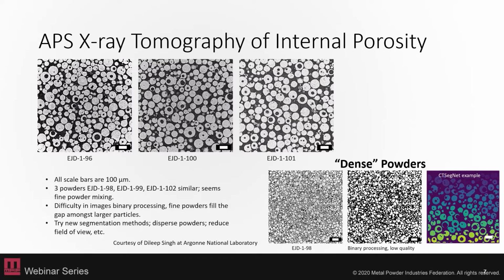He's collaborating with us on a current project and took these images to look at the internal porosity within these powders. All the scale bars are 100 microns, and you can see some similarities across these different powders that were produced by a commercial partner. There's some difficulty in getting these images processed, and this is an active area of research, but you can kind of see how you move through and get the black and white images and then do an image analysis to look at the powders that have these spherical pores on the inside, and then characterize those using some segmentation methods.